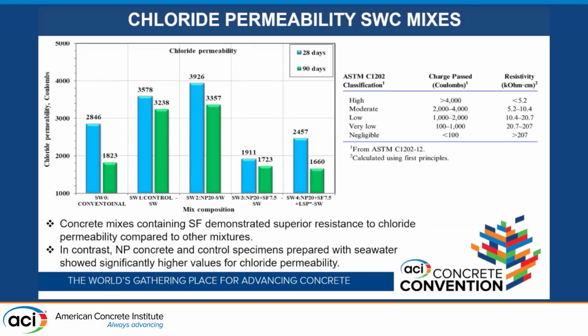Then moving on to chloride permeability, the concrete mixes with the silica fume demonstrated highly superior resistance to chloride permeability compared to other mixtures. And in contrast, the natural pozzolan concrete and control specimen prepared with seawater showed significantly higher values for chloride permeability.